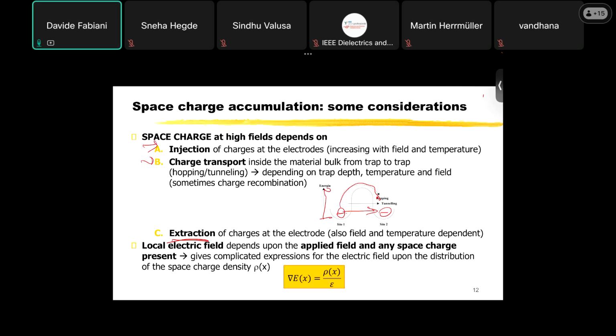So the local electric field is not uniform. Our electric field is not the one that we are thinking when we, for instance, divide the voltage by the thickness of the material. If we are in a plane geometry, we know that the electric field is uniform, and it's given by the ratio between the voltage applied and the thickness of the material. But this is the average field. This is not the case when we have some local charge present inside the material. In that case, the local field, the applied field, can be affected by the space charge that is present.